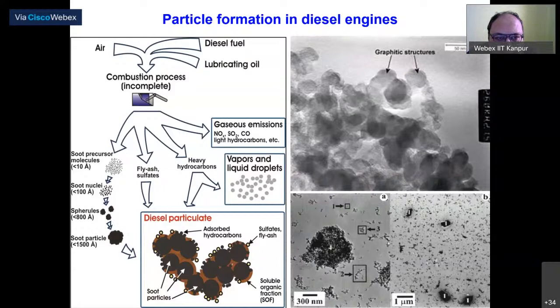So this slide basically tells you there's a mixture of air, diesel, lubricating oil. The initial set of particles which are forming are very, very tiny in size. So there are a bunch of them. When they come together, they coalesce and become bigger. They form stable particles on which other gases condense, and then you see the soot particles. So it is very complex. You probably have the elemental carbon core at the center, adsorbed organics on the top, and some amount of sulfate and fly ash and so on.